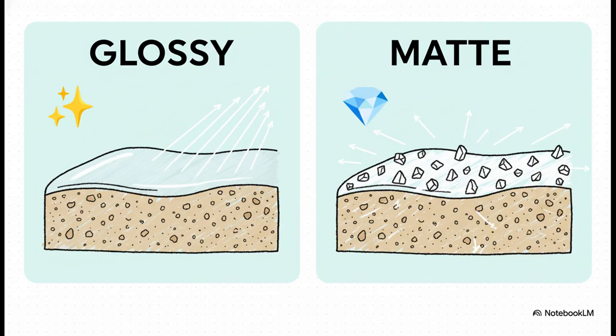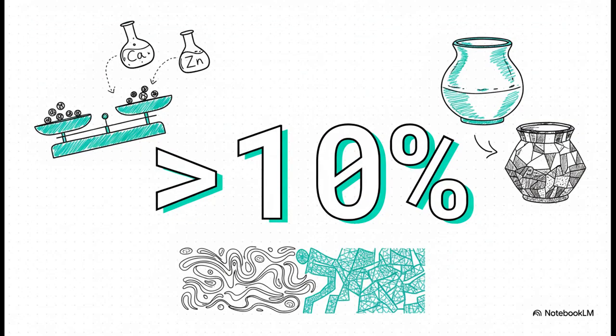It's a process called devitrification, where you intentionally create tiny crystals within the glass as it cools. It's those little crystals that scatter the light and give the surface that soft, non-reflective quality. And get this, it doesn't take much to tip the scales. Just crossing a threshold of about 10% for ingredients like calcium or zinc is often enough to push the balance from a glossy melt to a crystal-forming matte. That one simple percentage can completely redefine a glaze's entire character.